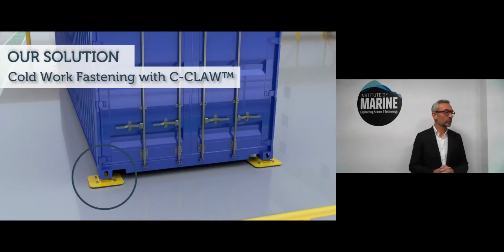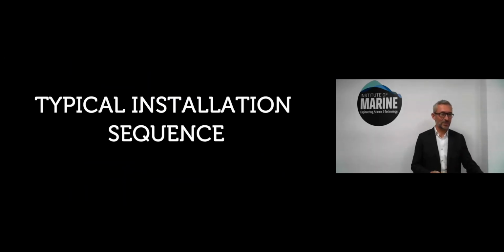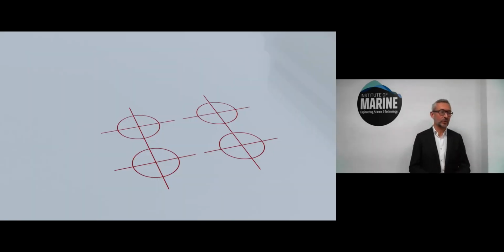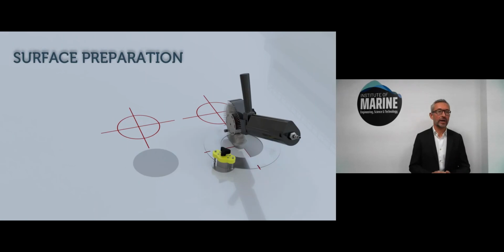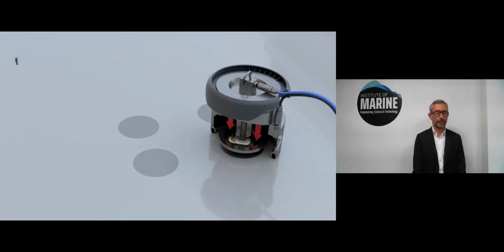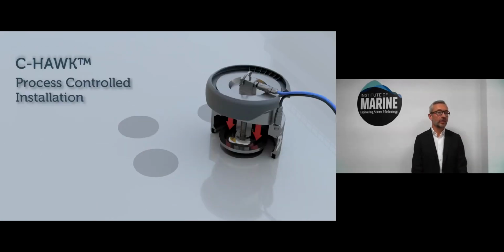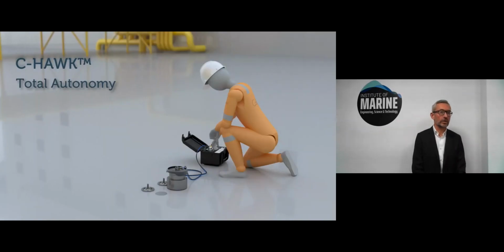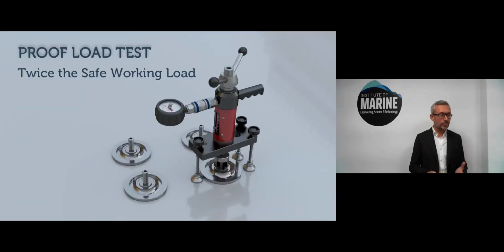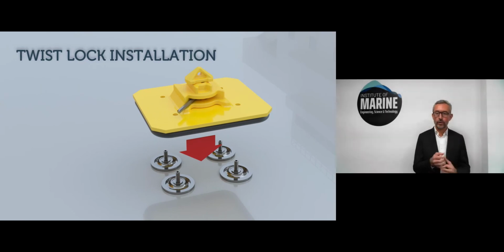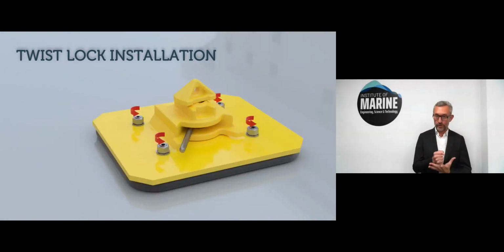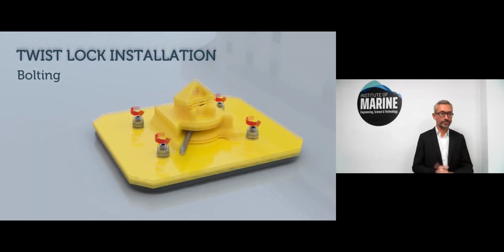So now I think you know the routine. Surface preparation, installation with the tool, proof load test if required, and then you remove the tool. Typically the capacity you have is 4 tons, and actually 1 ton per fastener for short-term loading is very conservative. If we pull on a fastener, usually the failure on short-term would be in the threaded rod at 6 tons. So we have quite a conservative safety factor.